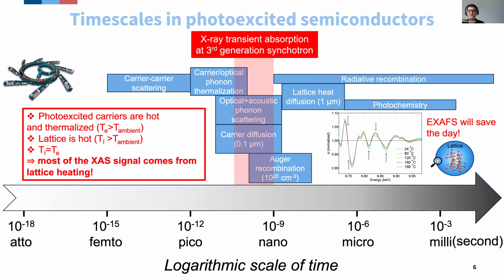And on a longer time scale, there is the exchange of energy between carriers and phonons by carrier-phonon scattering. And because this also has happened quite a lot before the 100 picosecond mark, now your charge carriers have started transferring energy to the lattice. And by doing so, the lattice heats up. So the state of your system when you actually do the experiment at the 100 picosecond mark is the following. You have photoexcited carriers that are hot and thermalized at a temperature that's higher than the ambient temperature. The lattice is also hot at a temperature that's higher than the ambient temperature. And you can, in good approximation, assume that these two temperatures, the one of the lattice and the one of the carriers, are the same.